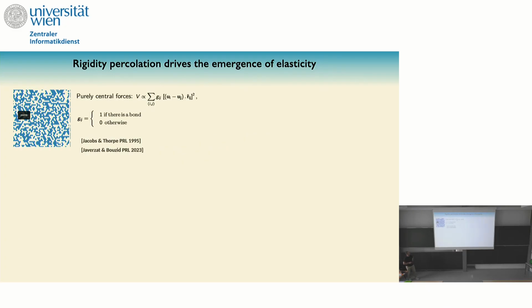Okay, so the first kind of model that you can do computationally is lattice models. Lattice models are very simple, but they are very powerful, and they have been very powerful in many fields. The idea is the following. Let's start with a triangular lattice, and then you fill it with particles with some probability. Or you start by filling the whole lattice, and then you deplete it with some probability. Then you say, when I have a contact between two particles, so a bond between the particles, the interaction is just a spring between them. And if I don't have any contact, there is no interaction. Very simple model.